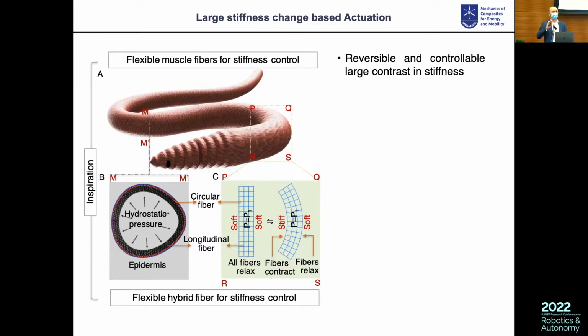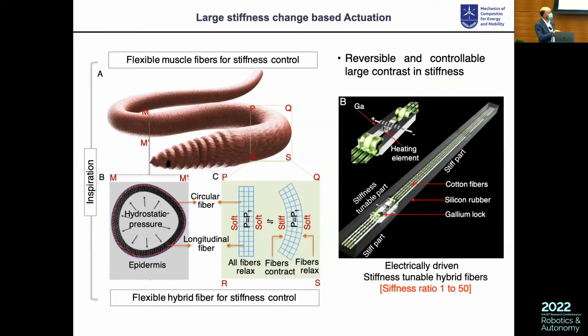If you are below 1 to 50 between the soft and the rigid phase, you are not going to control anything. So you need something that can be very stiff or very soft depending on the signal that you are putting in. For this, we generated a family of composite fibers, in which you have two phases: one stiff part and one part that can be melted, controlled by electrical melting.